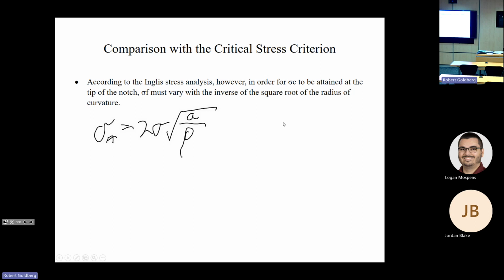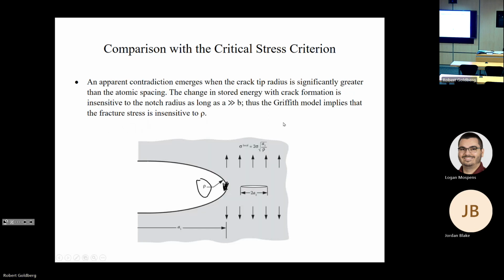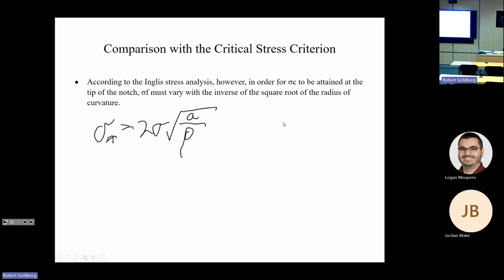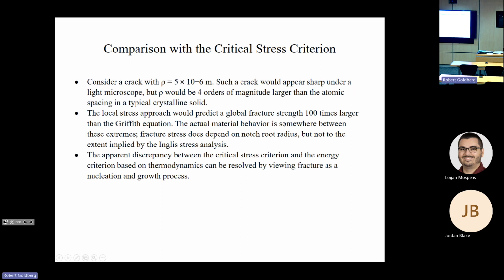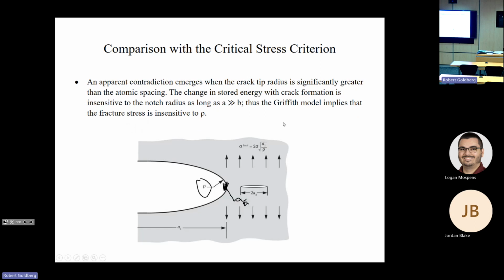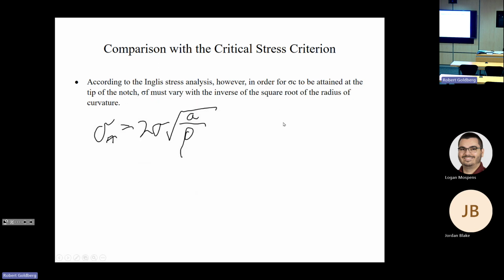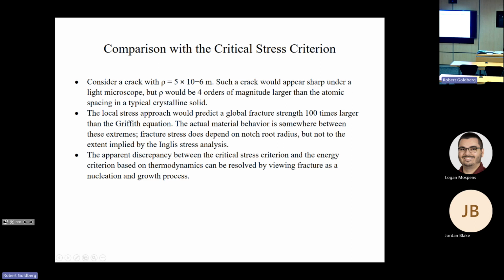So we talked about last time that with the Inglis criteria, this stress right here at the tip of the crack, sigma sub A, is significantly influenced by the radius of curvature. But in the equations we talked about with the Griffith criteria, there's nothing representative of the radius of curvature. So just for an example, consider a crack with this rho, this crack radius, given as 5 times 10 to the negative 6, so 0.005 millimeters if I'm doing my calculations correctly.